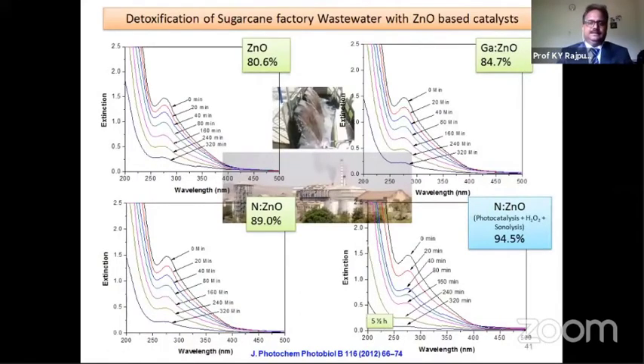We have even degraded seawater as well. Of course, it was not possible for us to degrade inorganic impurity from the seawater, but the organic impurity which was present in the seawater, it was possible to degrade. We collected samples of sugarcane factory wastewater, and with the help of zinc oxide and gallium and nitrogen doped zinc oxide, it was possible to completely get potable water out of this very dirty water.